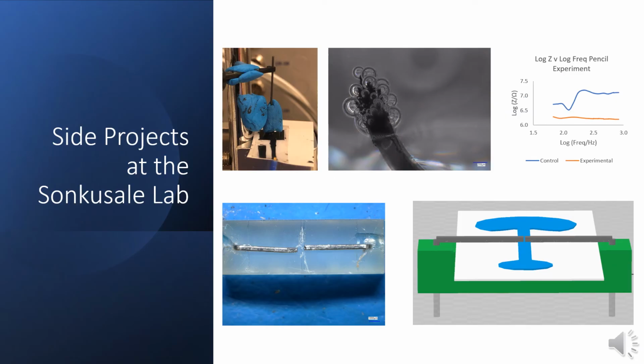Simultaneously, I've been working on a bubble assay using platinum nanoparticles immobilized to staple and pencil tips. My goal is to quantify the formation of bubbles using impedance spectroscopy on these surfaces. Impedance was selected because the air pockets that the bubbles form are very insulating, and hopefully, impedance spectroscopy can be used to quantify the formation of nanobubbles.